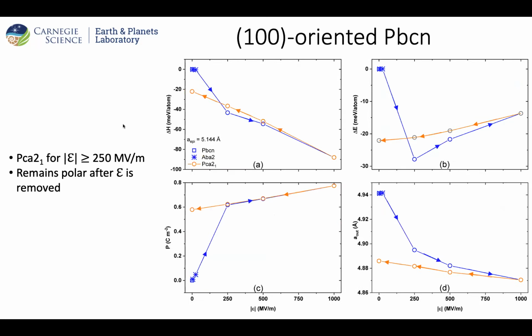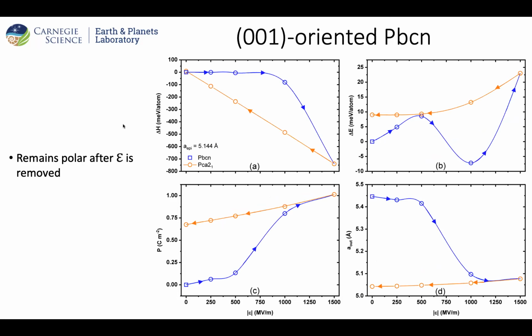We looked at another orientation, the 100 here. We see a similar case, but this time the electric field is much larger for the transition. Here it's at 250 megavolt per meter. And for the 001 oriented PBCN, it's around 1000 megavolt per meter. But the same story goes.